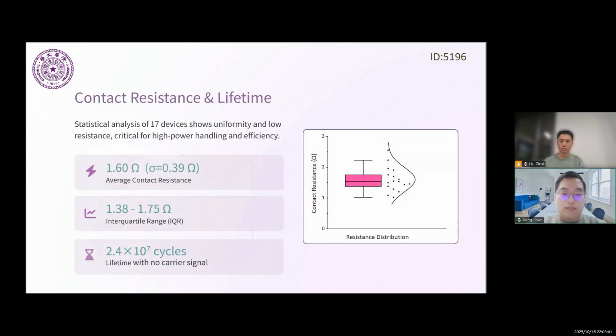We also did a statistical analysis of contact resistance across 17 fresh devices. This is what we get. Mean resistance is 1.6 ohm. The standard deviation is 0.39 ohm. The IQR is from 1.38 to 1.75 ohm. And in terms of lifetime, we've tested up to 24 million cycles without a carrier signal, and the switch is still working.